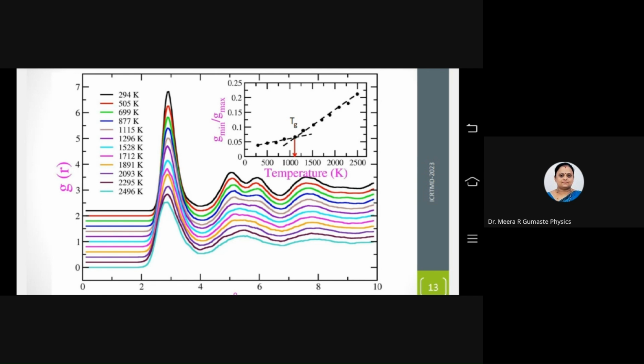As the temperature decreases, you can see here at the temperature of 1115 Kelvin, the second peak starts bifurcating. The two sub-peaks arise at a temperature of 1115 Kelvin and below that. At 505 and 294 Kelvin, you can see there are prominent two sub-peaks in the second peak. That actually marks the glassy structure. So glassy structures have a second peak which has two sub-peaks. And there is short range ordering, no long range ordering. That means no crystal is formed. So this is an amorphous solid. And to calculate the TG, the formula is that we have to plot g min by g max versus the temperature.